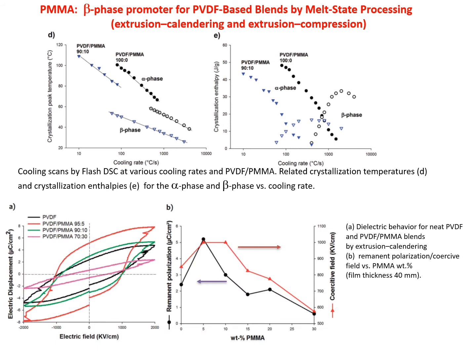And of course, the DE system shows that with PVDF, which is the black one, you have a ferroelectric system, but when you add more and more PMMA, you can see that you are going to a piezoelectric system. And at only 5%, the remanent polarization is already very high, showing that indeed it's not so important to add a big amount of PMMA in your system.